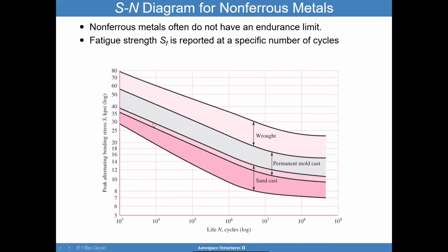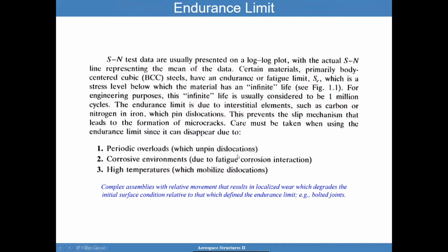And you can see here that at very low stresses, you still have finite life. The endurance limit is usually presented in a log-log plot with the actual SN line usually representing the mean of the data. Certain materials, primarily BCC steels, have an endurance or fatigue limit, SE, which is a stress below which we believe the material will have infinite life. For engineering purposes, we could consider infinite life to be 1 million cycles, but I will warn you against that, because some applications such as turbomachinery could reach 1 million cycles fairly easily.